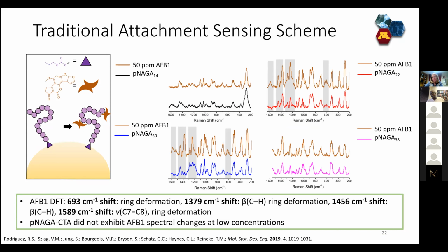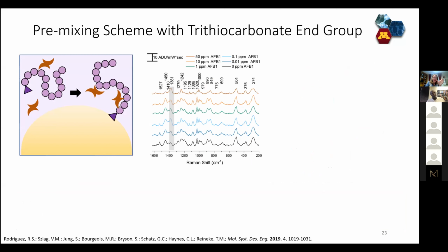And you'll notice in the red and blue spectra that there are some new bands that actually appear when we put in the aflatoxin target. They're highlighted by that gray box. So that was exciting. It seemed like our polymer was actually helping us to detect this. So we proceeded with that 22 repeat NAGA and tried different concentrations of aflatoxin. So when you develop a sensor, you always try and figure out, what is your limit of detection. So again, in black is just the polymer. It's our negative control. And as you go up, you're getting increased concentrations of aflatoxin.